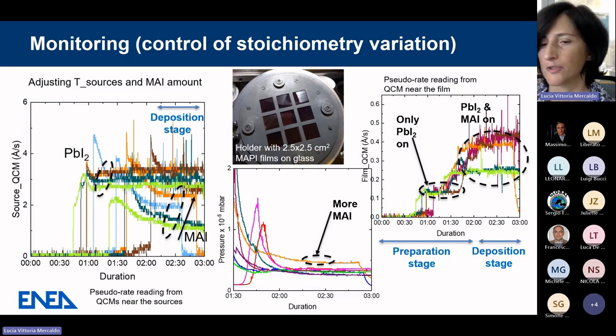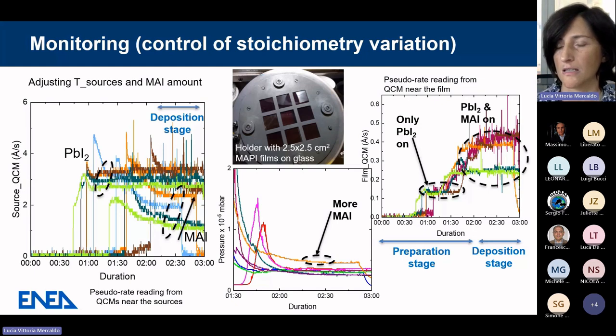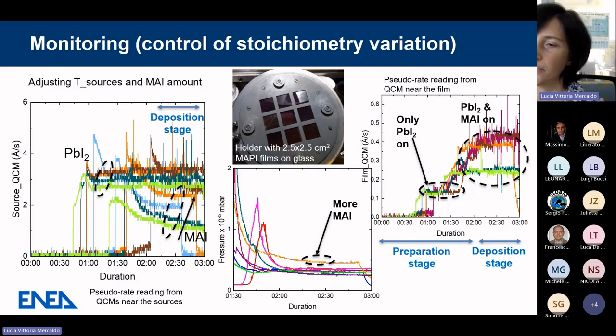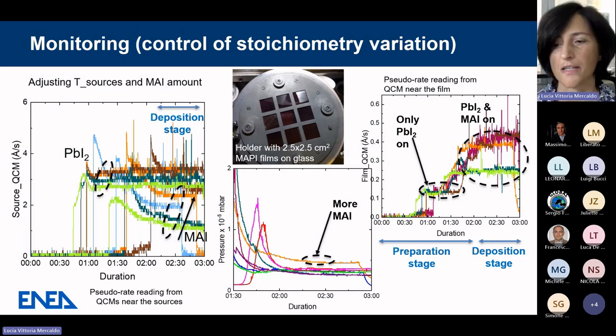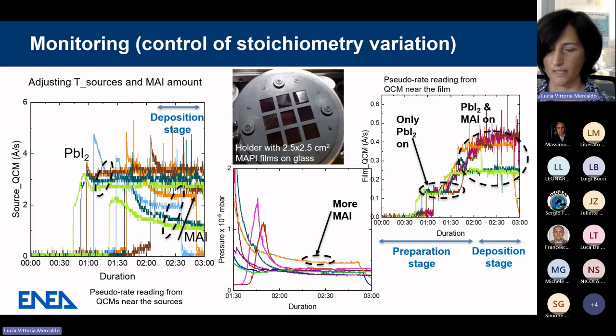Another parameter that is really important to check, especially when dealing with organic precursors, is the pressure in the chamber. And so we can see here, for example, in this graph in the middle, that when there is more organic precursor, the pressure is higher in the chamber, so one can adjust the conditions by looking at all these parameters. So what is important is to always work with measured amount of precursors and monitor pressure and pseudo rates.